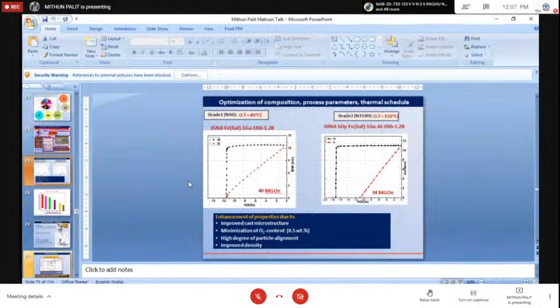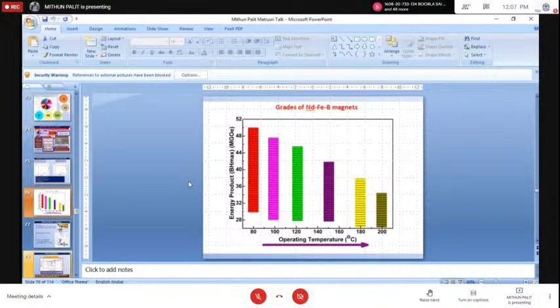And further, these flakes obtained from this high cooling rate process are used for further PM processing. You can see just by doing that, the energy product can be increased from 34 to 40 megagauss-oersted. And there are some other process techniques also. We can use hydrogen also during compaction and other things. And there are different grades of material.